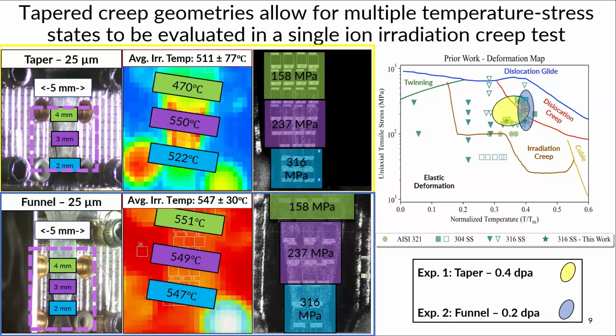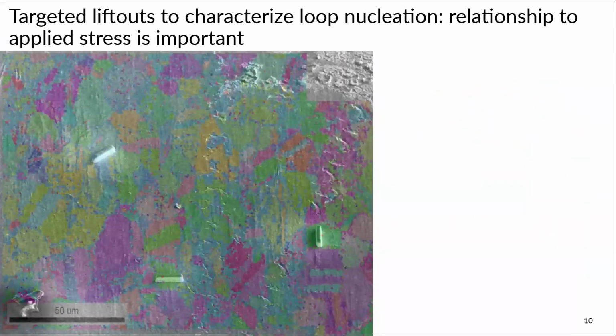And the microscopy aspect, I'll just be focusing on this experiment. It was irradiated to 0.2 dpa. So basically, it's really important for the microscopy aspect. We know that there's loops and dislocations that form on habit planes or close packed planes in FCC structural material.